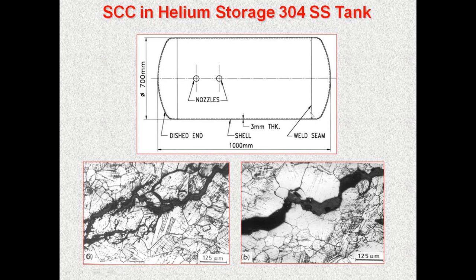Unfortunately, they used normal water and not DM water, and that contained a lot of chloride. Because of this weld, which has not undergone any stress relieving, the residual stress produced after welding, plus the chloride that was present in the water that was left out after the hydro test, led to the stress corrosion cracking. So this is a very important type of corrosion that happens, and the entire tank has to be discarded.